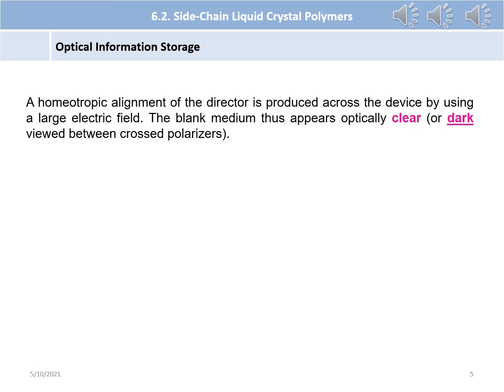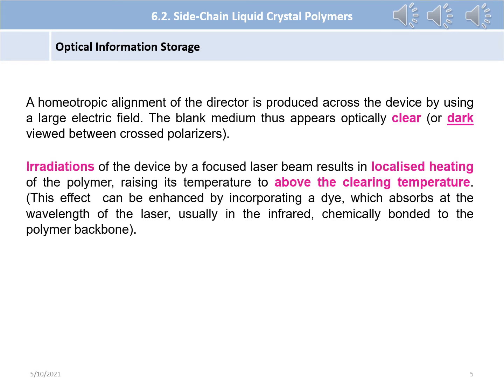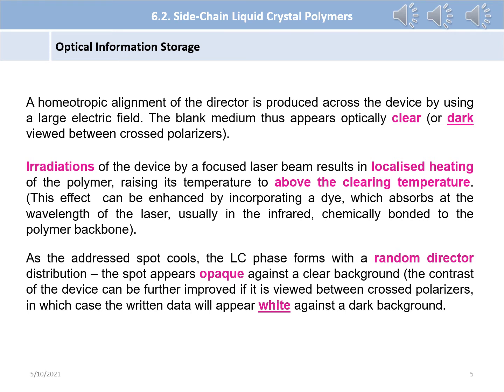A homeotropic alignment of the director is produced across the device by using a large electric field. The blank medium thus appears optically clear, or dark viewed between crossed polarizers. Irradiation of the device by a focused laser beam results in localized heating of the polymer, raising its temperature to above the clearing temperature. This effect can be enhanced by incorporating a dye, which absorbs at the wavelength of the laser, usually in the infrared, chemically bonded to the polymer backbone. As the addressed spot cools, the liquid crystal phase forms with a random director distribution. The spot appears opaque against a clear background. The contrast of the device can be further improved if it is viewed between crossed polarizers, in which case the written data will appear white against a dark background.